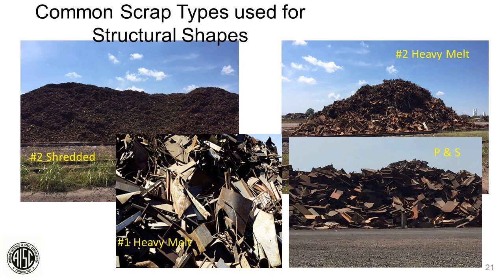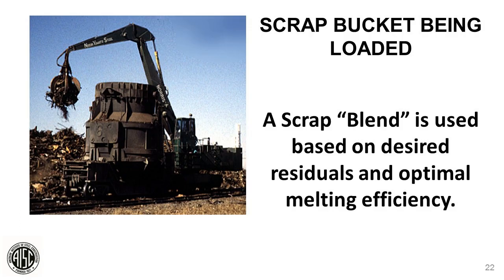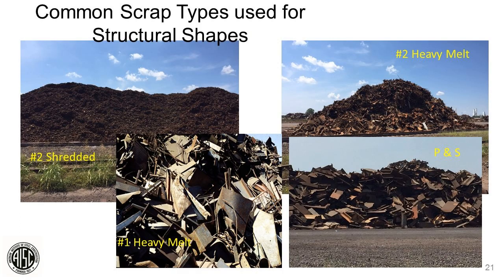everything that goes through a shredding facility, and the non-ferrous product is separated off, and the ferrous product goes to us to be melted. The benefit of this is it's very dense, loads very well, and the copper is sorted out typically through the non-ferrous separators. We don't have as much copper coming through that scrap. And in the front left, again, we go to number 1 heavy melt. It's another primary scrap type. That's a premium product. It's very dense, very heavy, typically very clean as far as residuals.